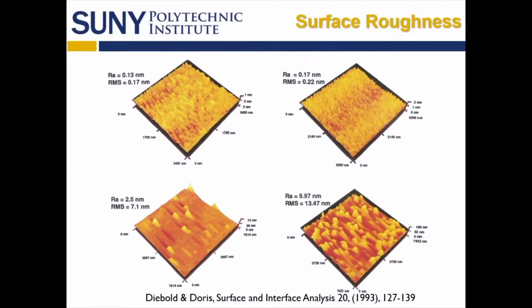All right, so what we have here are silicon wafer incoming surface, about an angstrom, 0.3 of surface roughness, and what you see are the results of 3 different vapor phase cleaning studies. And way back then, this was very important because people were worried about silicon dioxide and silicon oxynitride gate dielectrics, and the interface between the silicon and the silicon dioxide needed to be smooth to have the electrical properties of the transistor work well. And if you're interested in some history, that article is available online.